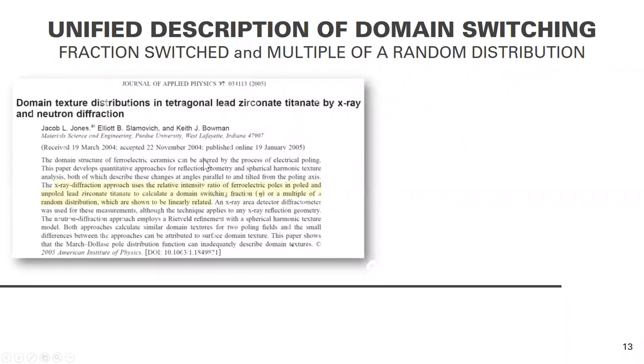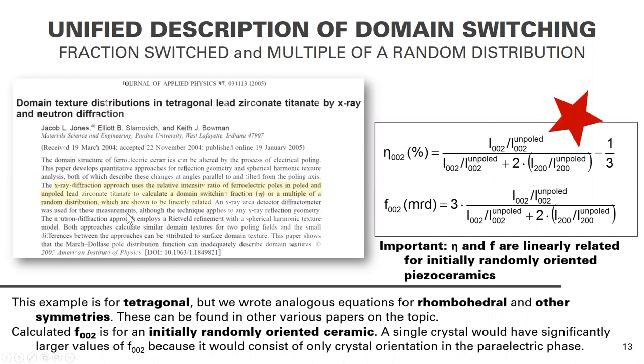And so I was very happy as a freshly minted PhD student to publish this paper. The most relevant text here is highlighted. The X-ray diffraction approach uses the relative intensity ratio of ferroelectric poles in poled and unpoled PZT to calculate a domain switching fraction, which we're representing as eta, or a multiple of a random distribution, or MRD, and we show them to be linearly related.